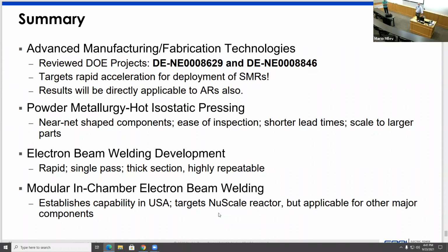We struggled a little bit with ferritic alloys, with low alloy steels, because they tend to pick up oxygen, and the silicon combines with that oxygen, goes to the grain boundaries, and you end up getting reduced toughness. We've been working on that. I think we've kind of got it figured out. We're doing a process called vacuum annealing to get rid of some of the oxygen out of the powders themselves. You could go to a VIM atomized powder, you can also get rid of it.